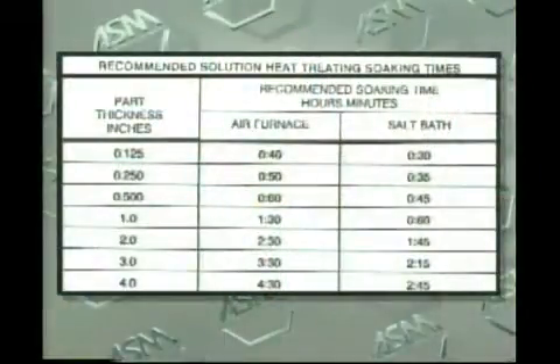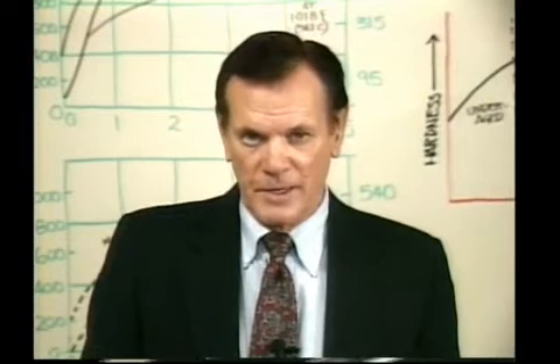The recommended soaking times for air furnaces and salt baths are shown here for wrought products. The primary requirement for soak time for wrought or worked alloys is the thickness of the material being heat treated. Thick section wrought products, such as plate and forgings, are generally heated at least 1.5 hours per inch of thickness. Much shorter times, 10 to 30 minutes, are adequate for sheet products.